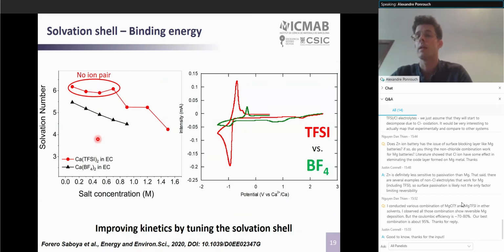So we expect that this difference in plating stripping kinetics is at least partly associated with the difference in solvation structure in the bulk electrolyte, that impacts the desolvation energy and therefore the plating and stripping kinetics. And we of course expect that this can also play a role in the de-insertion of divalent cation in cathode materials, where desolvation is expected to happen.